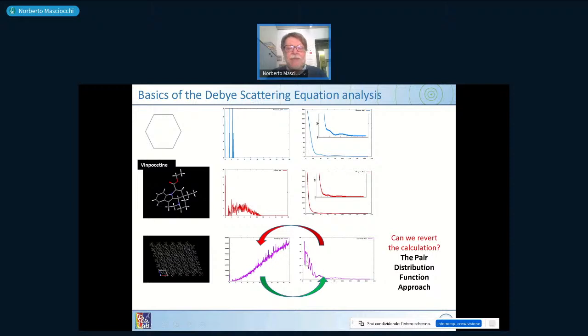So you have collected a data set, then you build a model, you can compute this histogram of distances and transform it with the Debye equation into the model pattern, and you can compare the model pattern with the real one. So the feedback is continuous. If the model pattern matches the real one, you're finished. If not, try to modify your model until you get a better convergence.